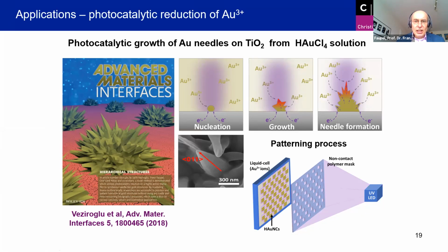They have excellent adhesion, and by tailoring the reduction conditions, by tailoring the type of solvent and other conditions, we are able to also control the shape of the particles. So we can easily prepare spherical particles, but we can also tailor the conditions such that you get, for instance, such needle-like structures, which are particularly interesting for catalysis and other applications. And since this is photocatalytically controlled, we have patterning ability. So we can use a laser or other light sources or masks to provide patterns.